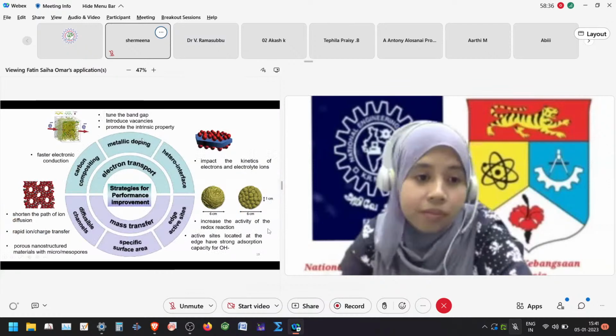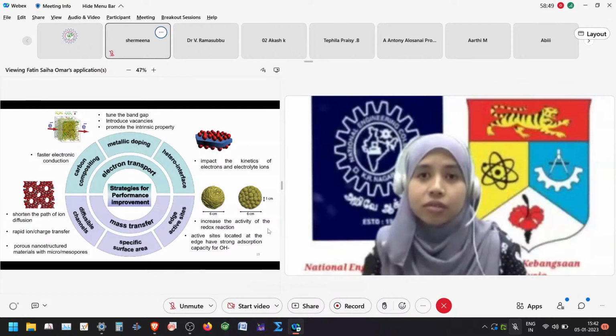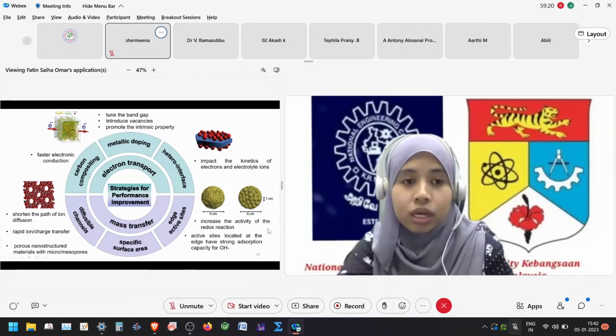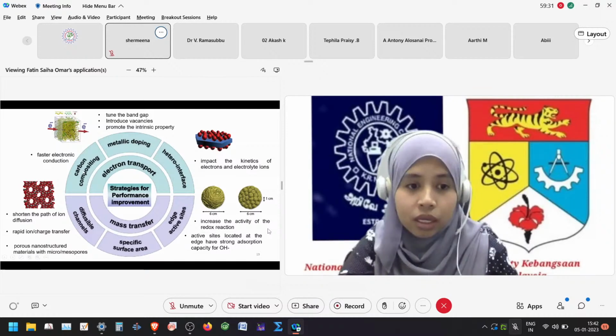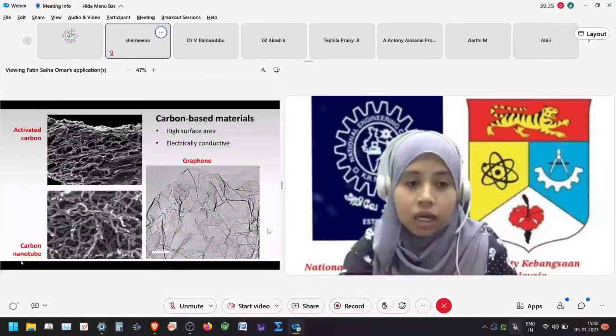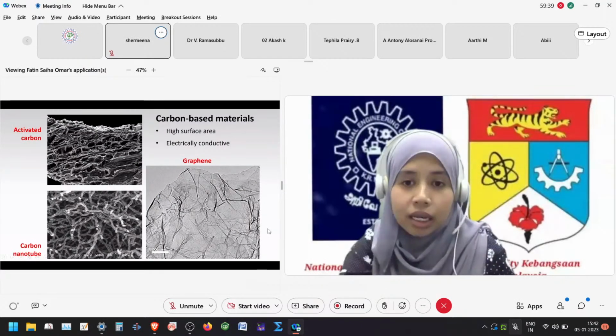And these are the strategies to improve the performance of the electrode. So typically when we use only one set of material, the material can offer either high specific capacity or high rate capability. Composite the metal oxide with carbon-based material to speed up the electronic conduction of the materials. And these are the most famous carbon-based materials. We have activated carbon and carbon nanotube, and the similarity that we can see from these two images is they have a lot of pores. Okay? And this is graphene. Graphene doesn't have many pores, but it offers a large surface area.